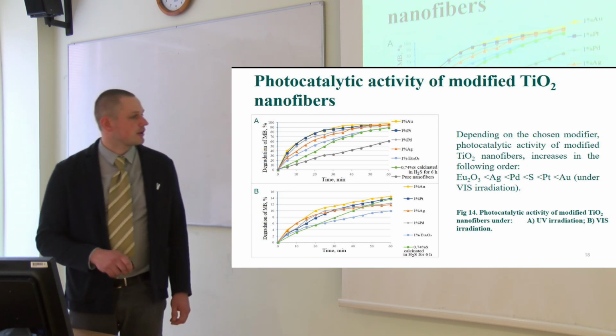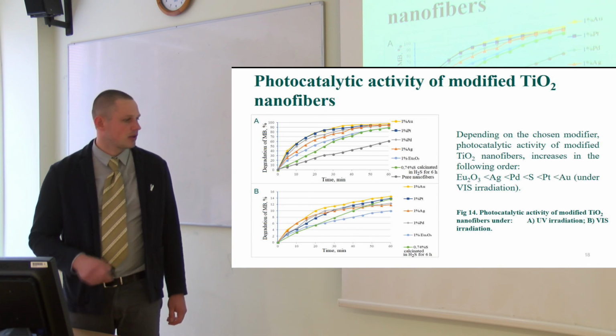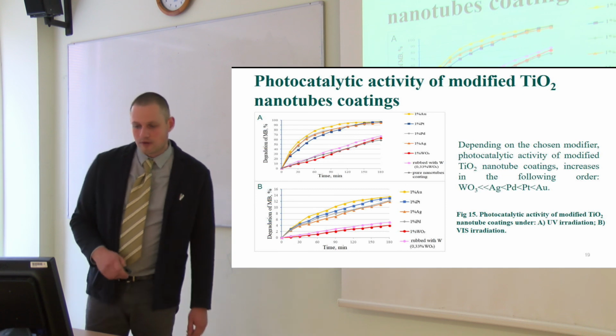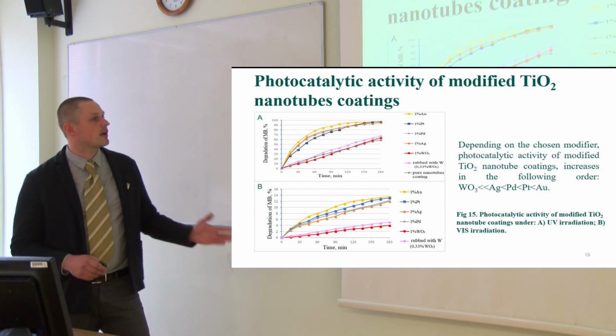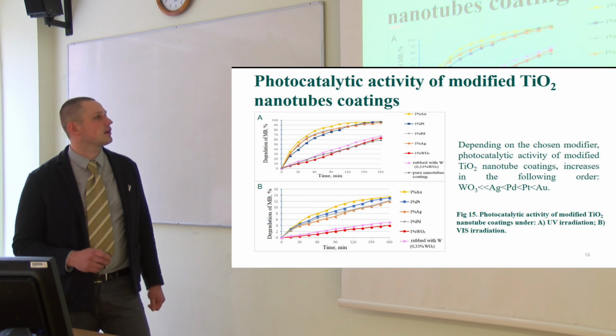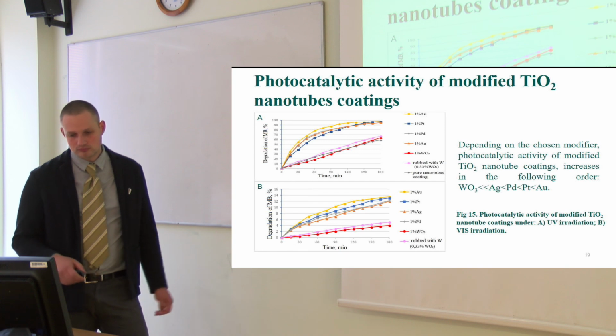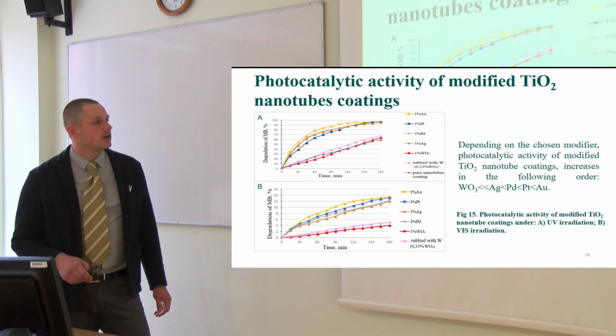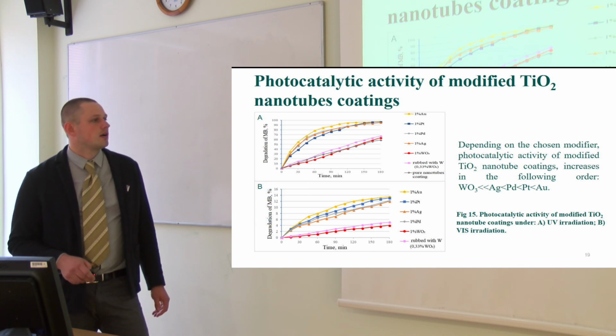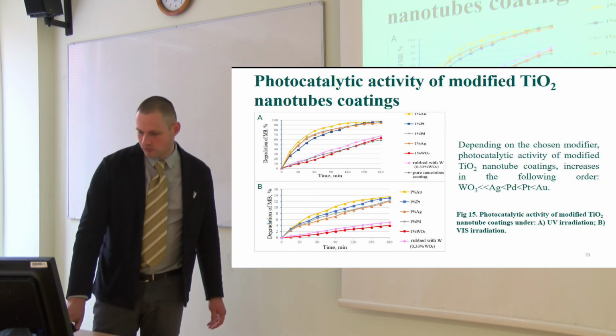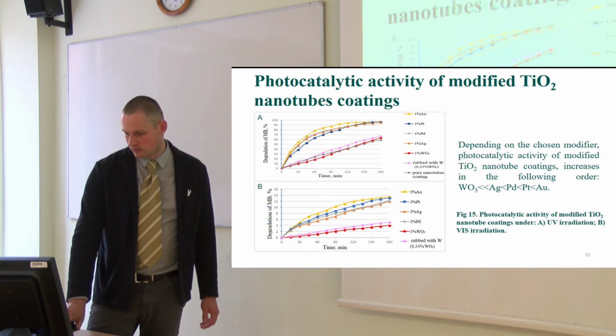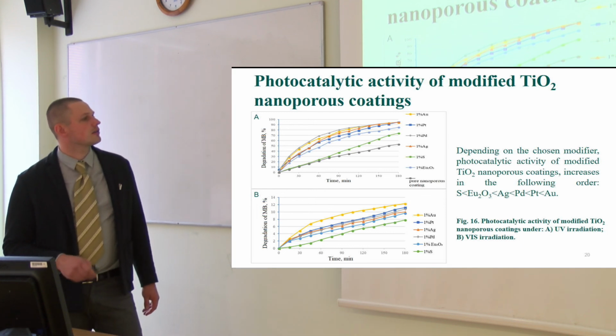So for us, the important graph is this one, because it's in visible light, and this is what we are looking for. Here you can see the same graph, the same measurements, but we are testing nanotube coatings, and the experimental times are 3 times longer. So this means that our nanotube samples are not so active as nanofibers were. So, and here activity increases in following order: tungsten oxide, silver, palladium, platinum, and the most active one is gold.